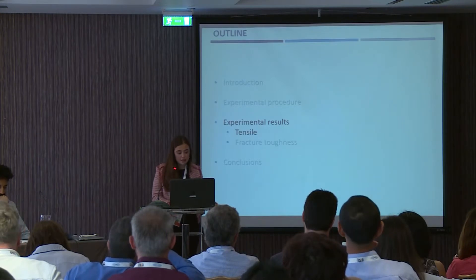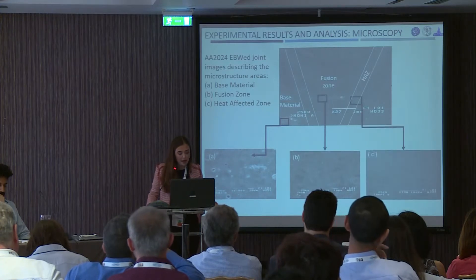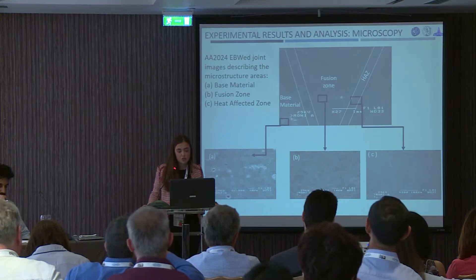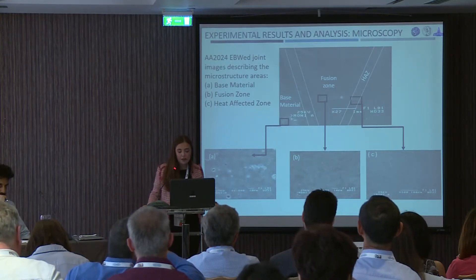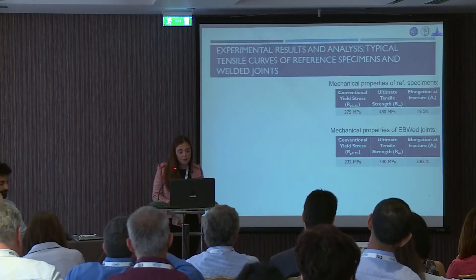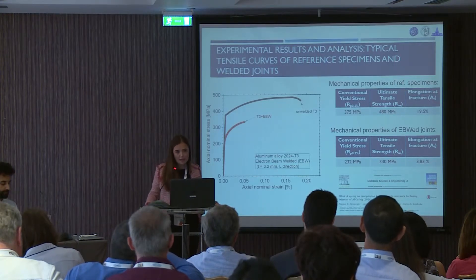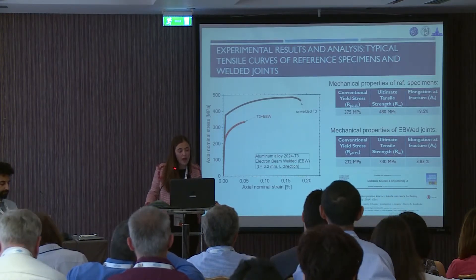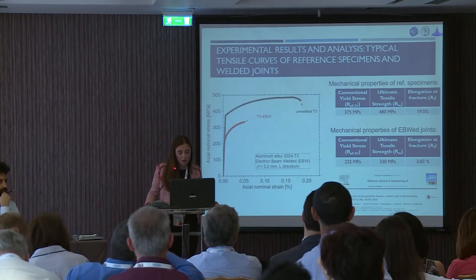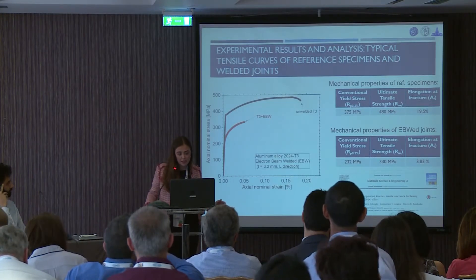Continuing to the results. Firstly, the microscopy photos allowed us to see the differences in the microstructures of the base material, the fusion zone, and the heat affected zone. We've seen the differences between the non-welded and welded 2024 aluminum alloy, and we've noticed that the yield stress of the aluminum alloy in comparison with the welded has an approximate 40% decrease.